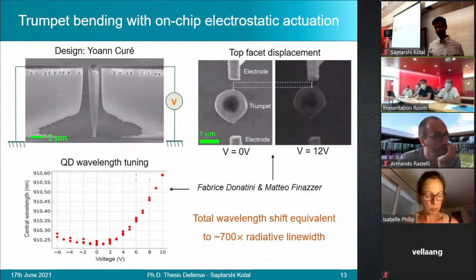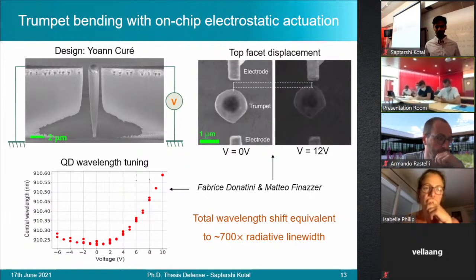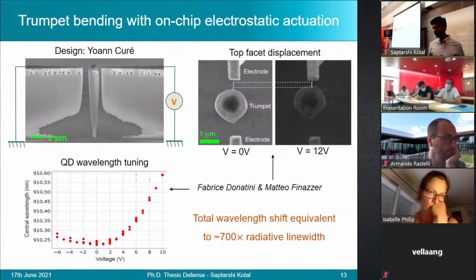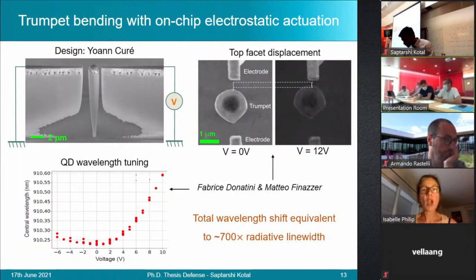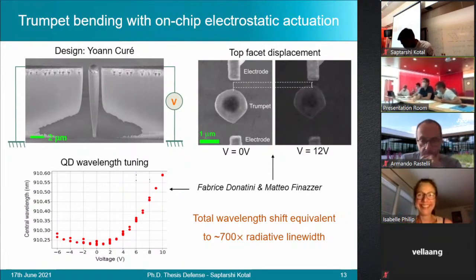The reason you mentioned is exactly right. The estimation of 1.5 milli-electron volts was the maximum that we could achieve with the given displacement of the top. And most likely this dot was much closer to the axis of the nanowire. Now, in terms of exactly determining what the position was, we haven't done that yet. We could consider doing it, but the technique has already been shown in Moon et al. And I can describe that if you'd like. Oh, if you wish. Yes, with pleasure.